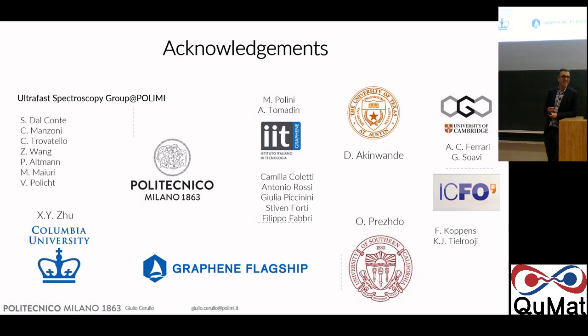Roy? You show that the interlayer exciton recombination is somewhat activated, it seems like there's a small energy barrier. Can you clarify what's the origin of that? Well, we see that it's temperature activated, and I think there is an interlayer breathing mode that somehow activates this, and it has a frequency which corresponds to an activation temperature in the range of maybe 100 Kelvin or so.